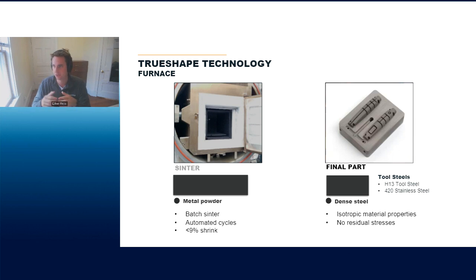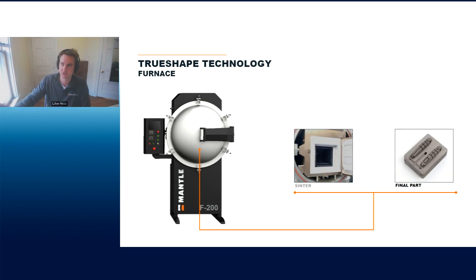And even with that 9% shrinkage, we're still able to hold plus or minus 1 thou per inch, which is really, really challenging generally in other sinter-based processes where they're shrinking more like 18, 19, 20%. So after printing is complete, you put the part into this furnace, it's going to run. And then what comes out is your dense, strong tool steel components like I'm holding here.